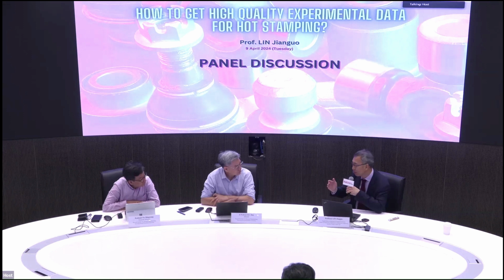In the real production process, just in your experiment, use air jet to do the cooling. Correct. Okay, you control 25 degrees per second cooling rate. Okay, we have got real production process. What exactly the media used for cooling rate? In the real manufacturing process, we just monitor the cooling rates of material. The minimum cooling rates of material is above the critical cooling rates.